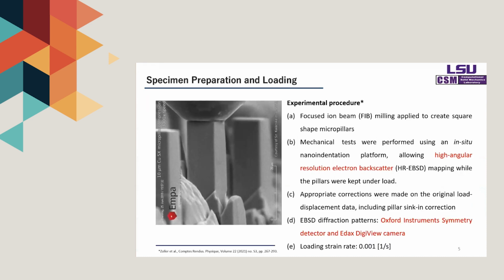Specimen preparation and loading. The in situ experimental procedure for the micropillar compression test is as follows. The square shape of micropillars is created by a focused ion beam, as shown in the SEM image. The compression tests were conducted using an in situ nanoindentation platform.